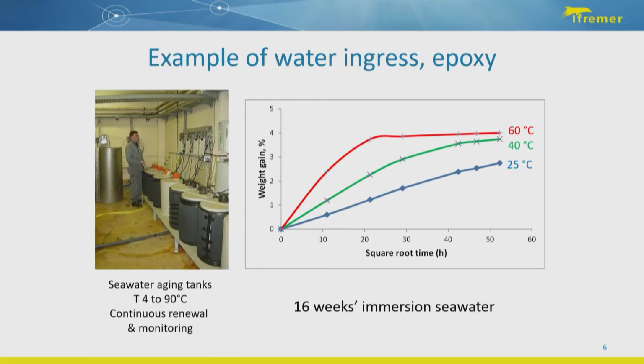traditional marine materials. So this is a marine epoxy. We have seawater aging tanks, which are at different temperatures. They're continuously renewed to try and avoid some of the biological effects. And we monitor them continuously. And essentially, we put samples in and we look at their weight gain. And that gives us an indication of how quickly water diffuses into the materials.